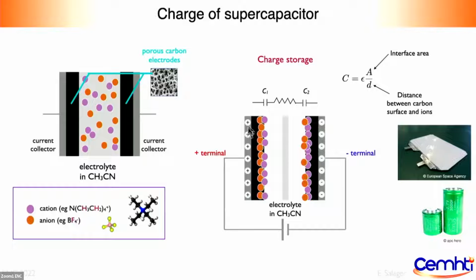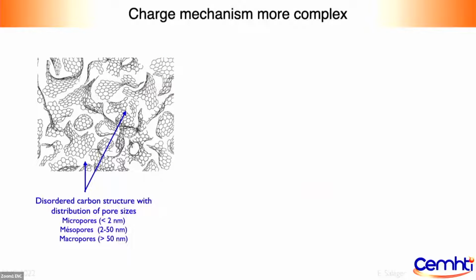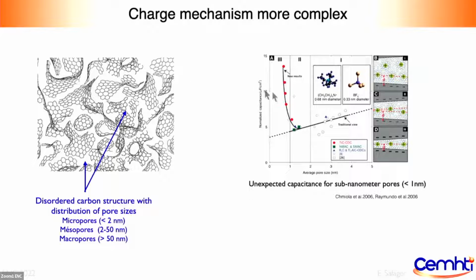So this looks quite simple, but actually the electrodes here are not plain. They're actually much more complex. There are different types of pores and different structures of carbons in there. And you can see that this is the capacitance as a function of the average pore size. And there was something really interesting going on with tiny, tiny pores, with a large increase in capacitance. And this was related to the removal of the solvation shell for the ions to go in so that they would get closer to the carbon and give a higher capacity.